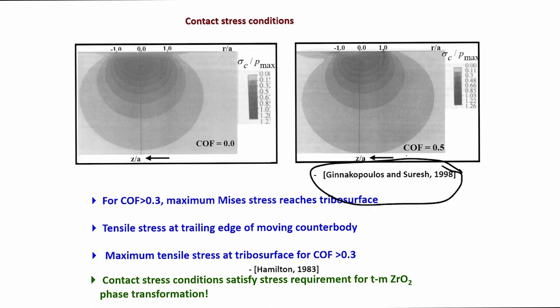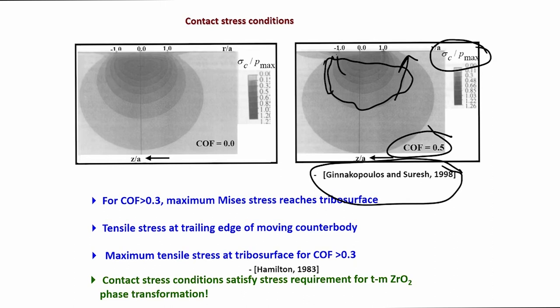And from there, one can do some calculations. Just to show you, this is one of the papers, I think it was published in Acta Materialia in 1998, from the group of Subra Suresh at MIT, showing this contact stress region. At the frictional surfaces, with a coefficient of friction of 0.5, the high contact stress region is shifted towards the tribological surface, and tensile stress is always experienced at the trailing edge of the moving boundary, and maximum tensile stress at the tribo surface is reached when the coefficient of friction is 0.3.